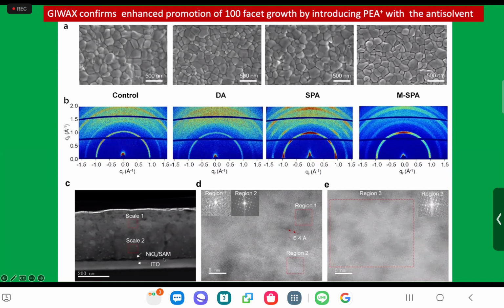And I wanted to point out to you again that we're going back to PIN structure, where the P-type hole selective support is a nickel oxide SAM. That's now becoming very, very fashionable, but we will see soon the nickel oxide will disappear, because SAMs are getting better and better. And SAM means self-assembled monolayer. It's not really a self-assembled monolayer. This is kind of like a spaghetti structure of the surfactant used.